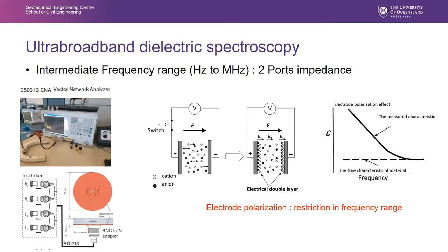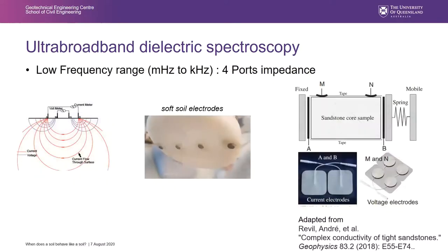And then the last method. A very, very accurate method for the low frequency is to use four-port impedance methods. In this case, we use two electrodes to inject current, A and B, and two electrodes to measure the potential. Because we don't measure when we inject current, we are not perturbed by this electrode polarization. So this can be used for soft soil with simple electrodes, or if we are more interested in sandstone or rocks, we use ECG electrodes with a spring to make sure that there is a good contact.